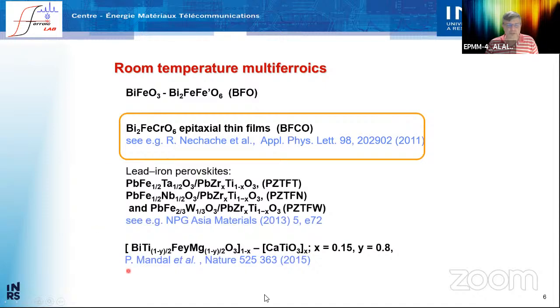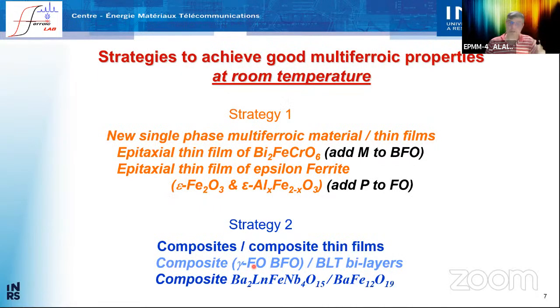Since then, some other materials have been made which are multiferroic at room temperature, but nevertheless, they are still very, very few compared to the number of ferroelectric or magnetic materials that you have in nature and in application. So how can you make multiferroic materials? Well, you have several strategies. In single-phase materials, you can try to add, between quotes, magnetism to good ferroelectric properties. That's what has been done with BFCO. Or you can try to add some good ferroelectric properties to a good magnetic material, which is what I will speak about with epsilon ferrite, the epsilon phase of Fe2O3.